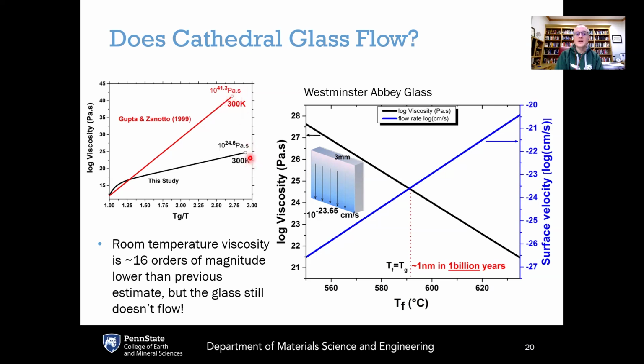And what we were finding is about another 16 orders of magnitude faster flow using real medieval glass, using our advanced characterization techniques and our advanced modeling techniques. So this more accurate estimate of the cathedral glass viscosity is about 10 to the 24.6 Pascal seconds. So that is a much lower viscosity, which would indicate that the glass is flowing much faster than what had been previously thought. But the other part that was missing was actually doing some fluid flow calculations.